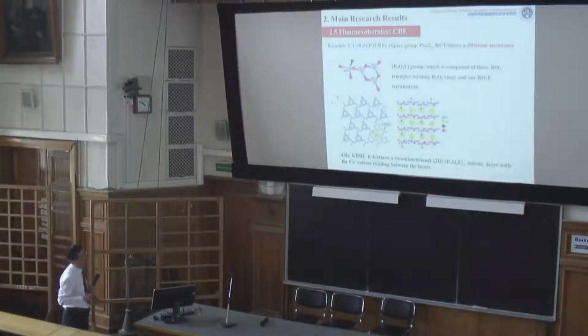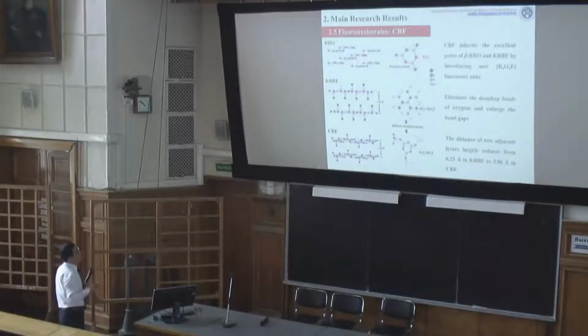And also we want to give a second example, using cesium to substitute ammonium. We got CBF. This compound also crystallized in Pna21, the same group. However, they show a very different structure. For example, as we know, why can BBO produce a large SHG response, 6 times that of KDP? Because in BBO there is this unit, B3O6. It means 3 BO3 connected with each other by sharing corners. This unit is a very good unit. It can produce a large SHG response and large birefringence.